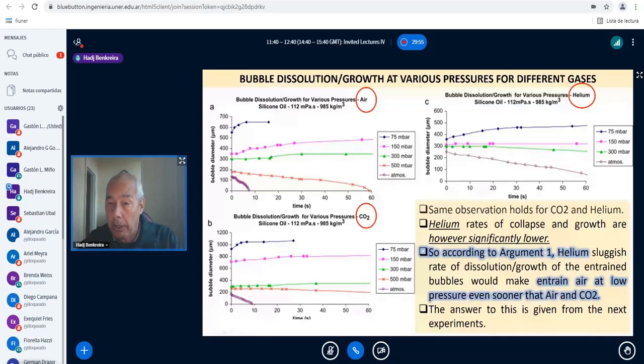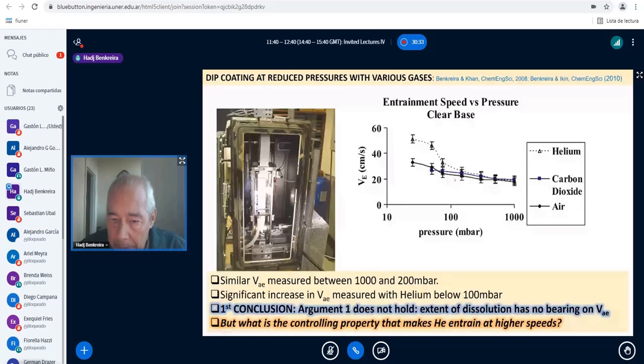So again, according to argument one, helium should be entrained at much lower pressure than air and CO2. So we went and observed the gas entrainment speed. With air, it will be the air entrainment speed. With CO2, it will be the CO2 entrainment speed. And with helium, it will be the helium entrainment speed, naturally. And there we have it. Quite the opposite. In fact, when we reduced the pressure, the gas entrainment speed increased.